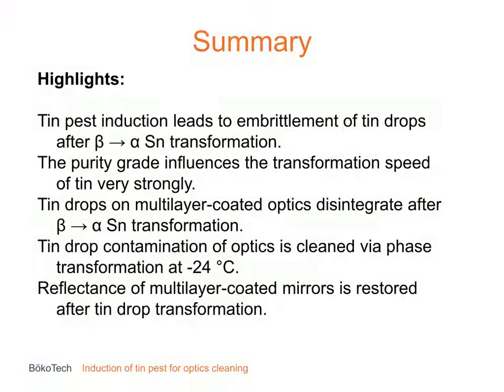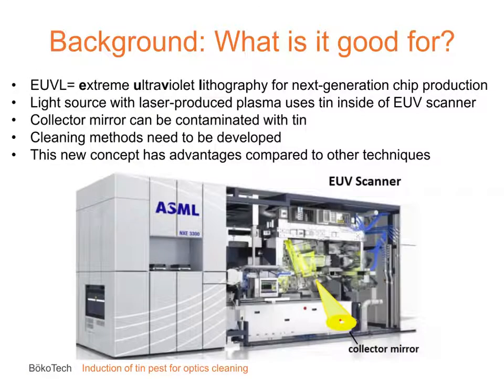By induction of tin pest, the drops crack into pieces. High purity tin is required. The transition is faster for higher purity grades. Tin drops deposited on multilayer-coated optics disintegrate into pieces after transformation. Sensitive optics can be cleaned by the phase transition at minus 24 degrees centigrade. The reflectance of multilayer-coated mirrors is restored by this cleaning method.